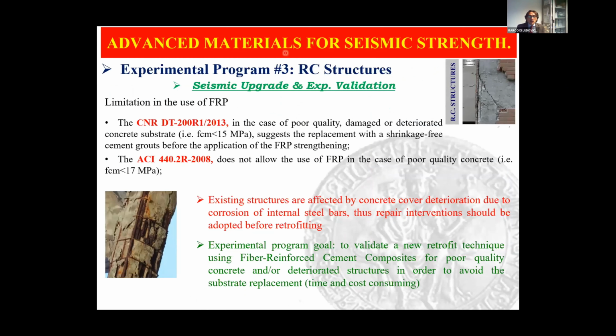Finally, experimental program 3. There are some cases in which FRP could not be the best solution, especially when the concrete is very poor, damaged or deteriorated, because in this case it is necessary to apply FRP on a better substrate. And so the idea is, why do we not use fiber reinforced cement composites in these cases? Why do we not use a thin jacketing made of fiber reinforced mortar cement composites, in order to remove the concrete cover and apply this layer without any other reinforcement?